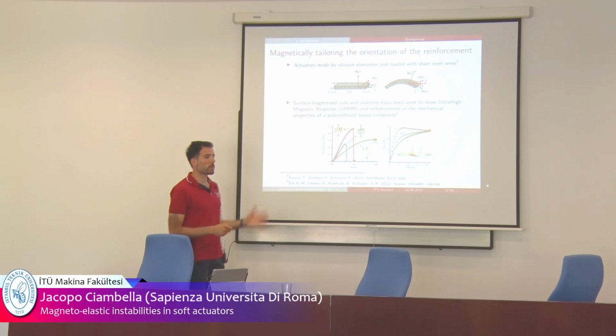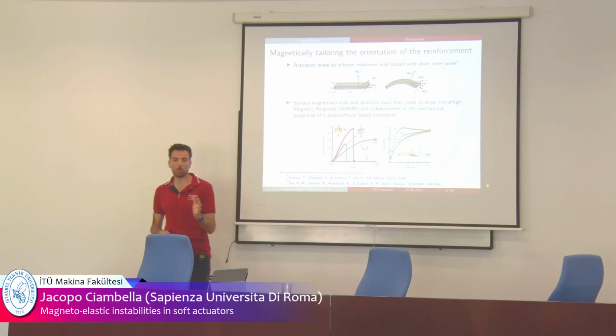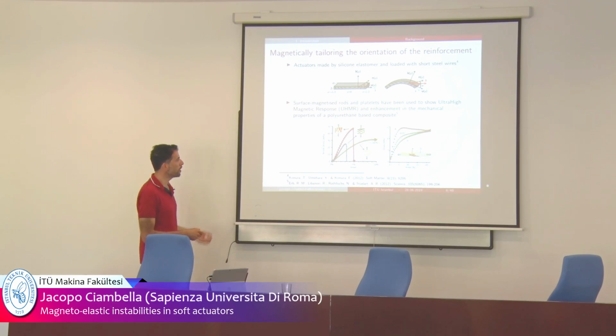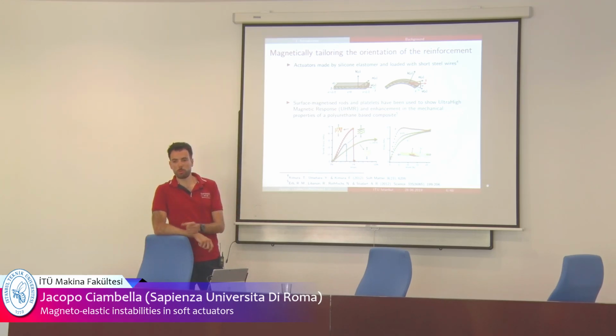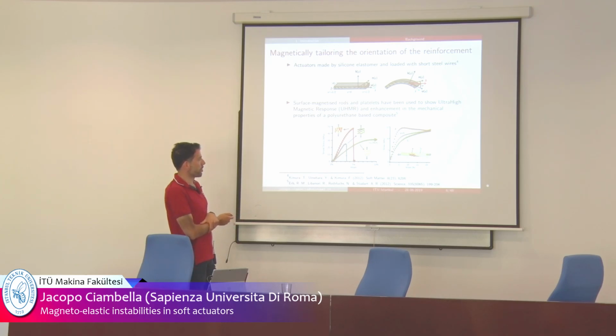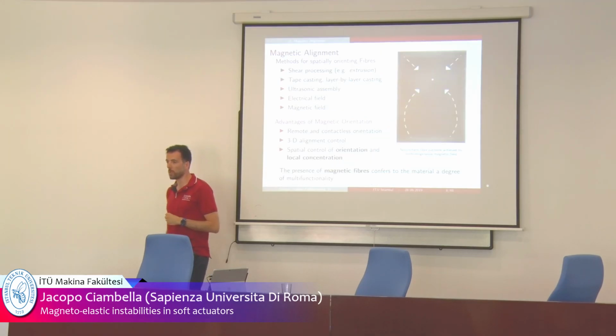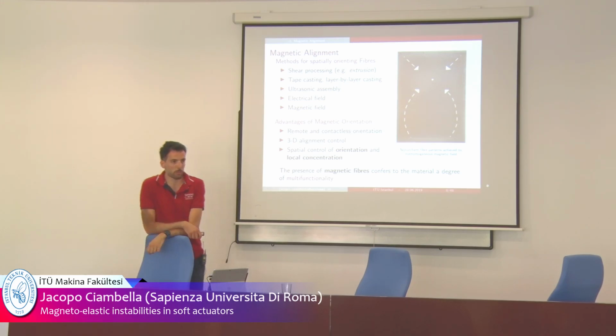Normally, when you orient reinforcement inside a material, you also control the mechanical properties. This is an example of an epoxy base where they use what they call ultra-high magnetic response particles. So these are platelet-like particles which have been treated to respond to the magnetic fields, and they were able to orient them, okay, and they obtained different tensile properties. For instance, if the particles are oriented along the load direction, they get a much higher stiffness in a composite material. The most common way is by shear processing, so extrusion.